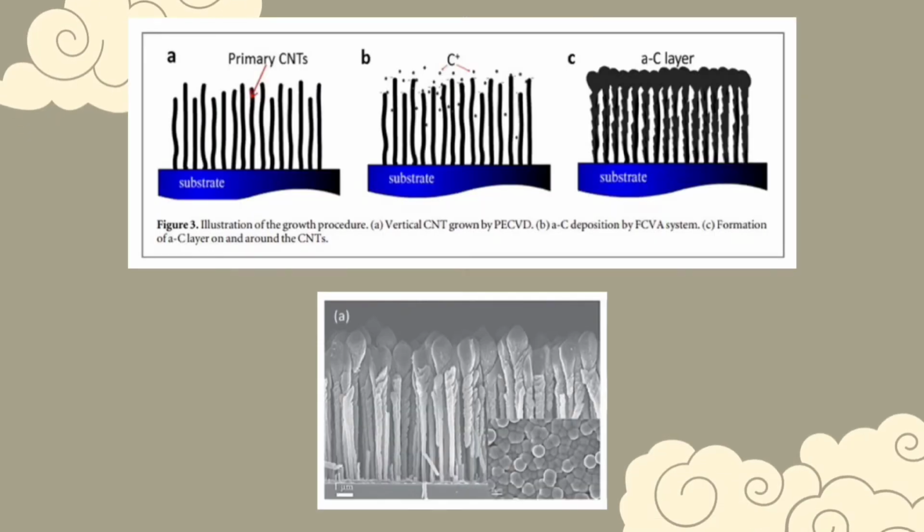As shown in figure 3, in the case of deposition of C on the CNT arrays, a C layer and spheres were formed on the CNTs because the high-energy positive carbon ions were accelerated to the side walls and tips of the tubes. As deposition continues, the nanospheres on the tips of the CNTs increased in size rapidly because of the higher charge density on the tips, as shown in this figure 6a. The top layers formed on top of the samples adhere very well by covalent bonds to the tips and the side walls of the tubes.